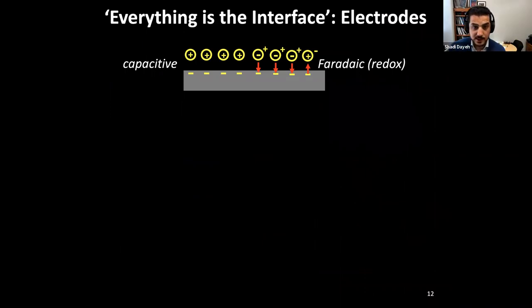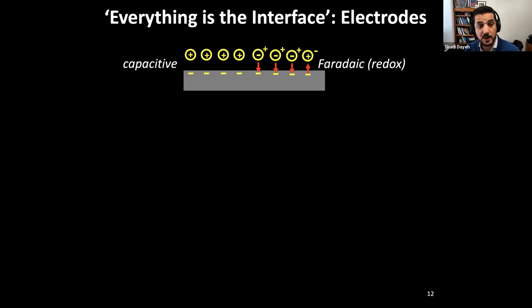So this is similar to many of the problems that we face in engineering, where we know that the interface is really everything. It overwhelms the bulk properties of the materials. So how do we couple the neural activity? Neural activity could be understood as motion of ions, or ionic currents in the medium. And we have a metal which we are using to sense this activity. We can sense that motion or the potentials from these ions either by capacitive coupling or with a direct charge transfer with the Faradaic redox reactions.